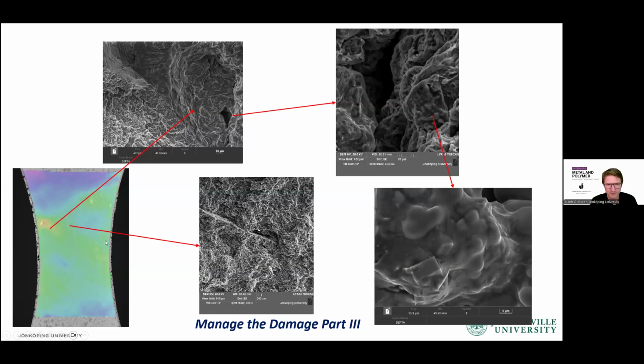There are multiple points where we can see this, and you can see that on the top region here, when we zoom in, you see the oxide quite clearly. And as we increase the magnification in the SEM, we can see that the oxide is really draping the microstructure, both the dendrites and the intermetallic phases that you see in the microstructure here. Also in the center, we see that there's kind of an oxide which is also extending into the material perpendicular to the fracture propagation which has taken place.